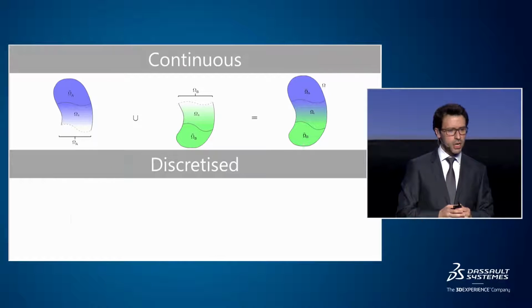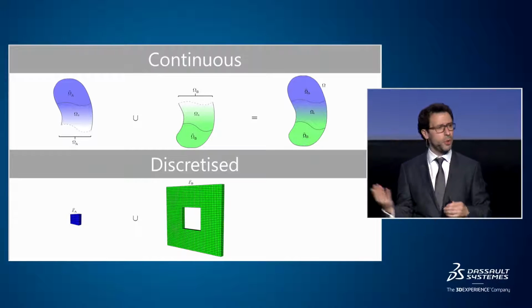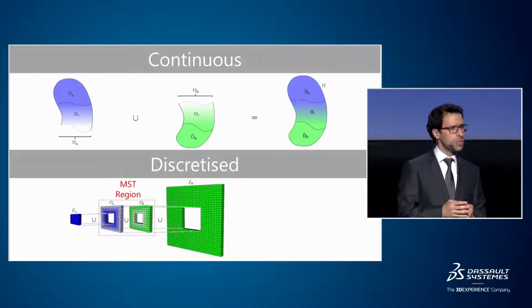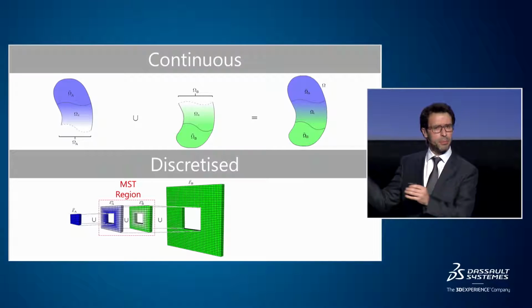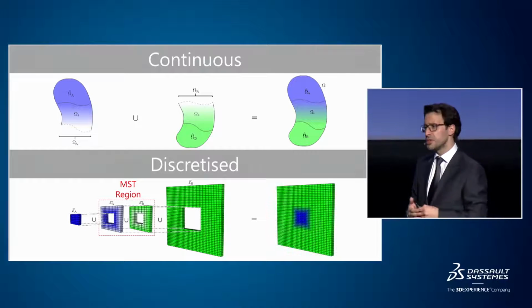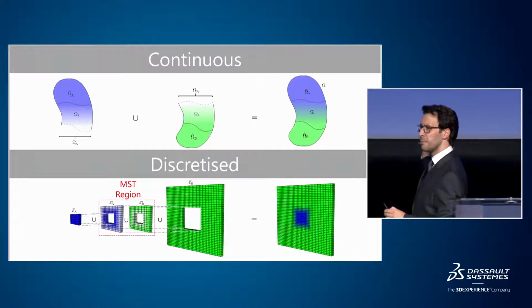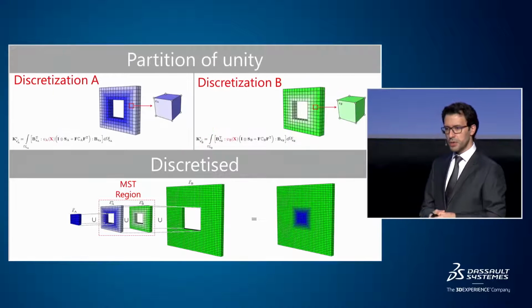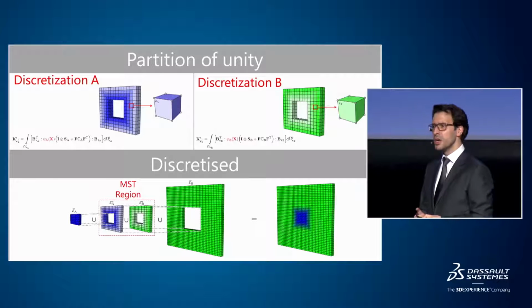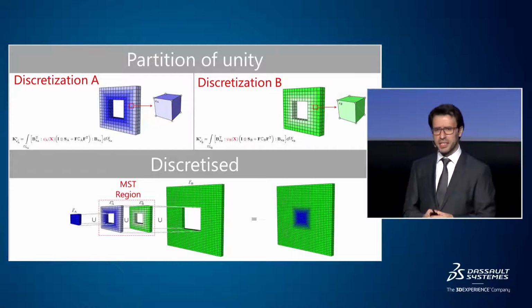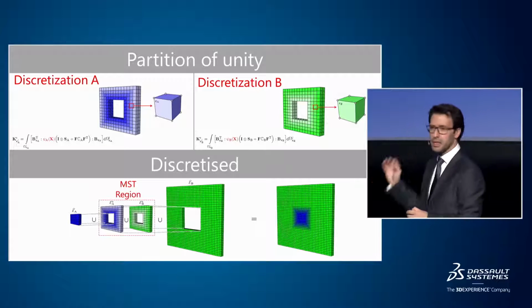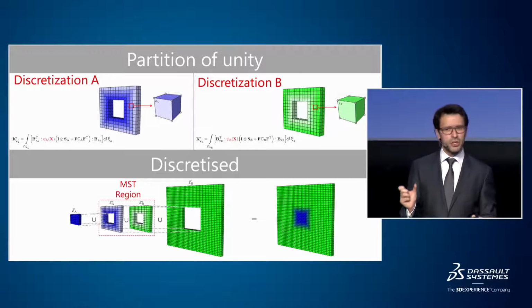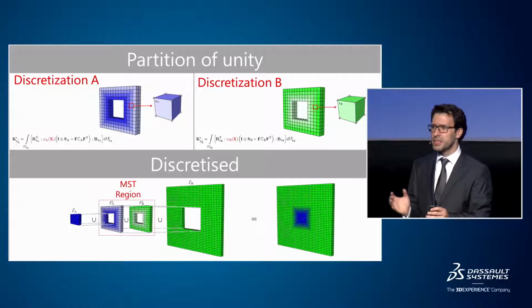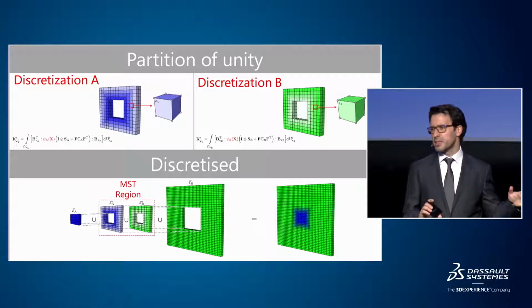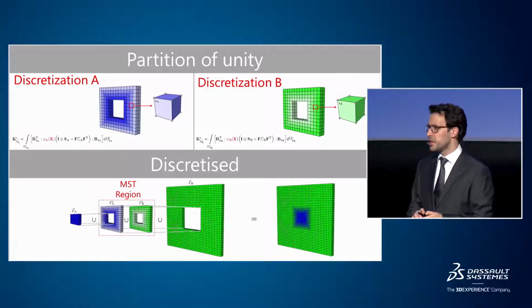In a discretized world, what we have is 2 different meshes, so the mesh in green and the mesh in blue, together with a region in between where one mesh progressively disappears and the other one progressively appears, so that we have this nice result of one mesh blending into the other. So how do we get the blending elements to occur? Well, when we define the stiffness matrix and the mass matrix, we have these functions psi that you can see there in red, which are just weight functions that verify partition of unity so that we get the correct physics, and they can be defined with a level set method so that we get the blending region in space done efficiently. So this is the theory.